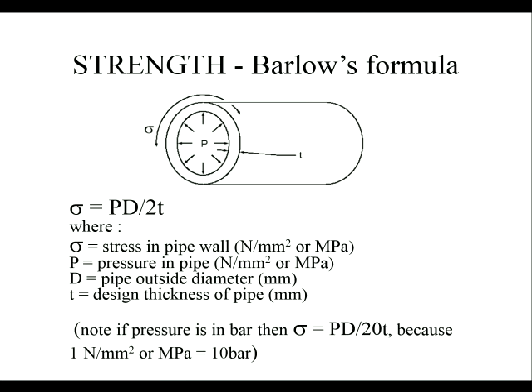of stress are pascals, or 10 to the 6th pascals, megapascals, which is just the same as newtons per millimetre squared. So if you measure the cross-sectional area in millimetres squared and you measure the load in newtons, you can get the stress in megapascals directly. So if we measure everything in millimetres, it becomes easy.